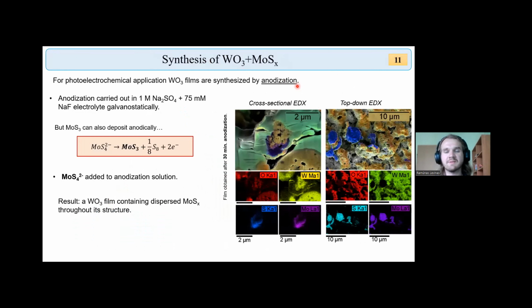Now, regarding the second part of my presentation, we synthesized tungsten oxide and molybdenum sulfide photoanodes. These composites were synthesized by anodization. So by anodizing tungsten in the following electrolyte, we obtain tungsten oxide. However, if tetrathiomolybdate, this is only an ion, is added, it can deposit anodically, the process also called disproportionation, into molybdenum trisulfide with some elemental sulfur also depositing. The result is essentially a composite of mostly tungsten oxide, with molybdenum sulfide dispersed, well, in some way throughout the material, as shown by these EDX maps, both cross-sectional and top-down.